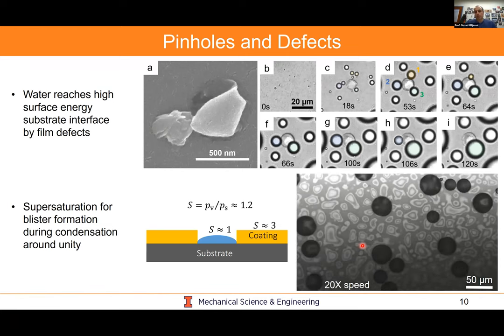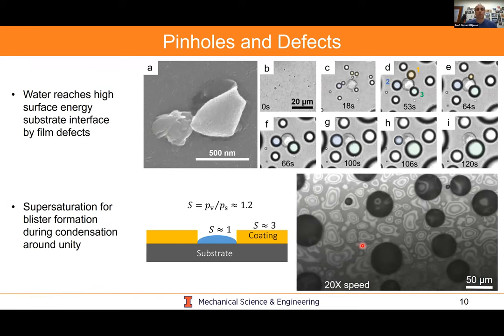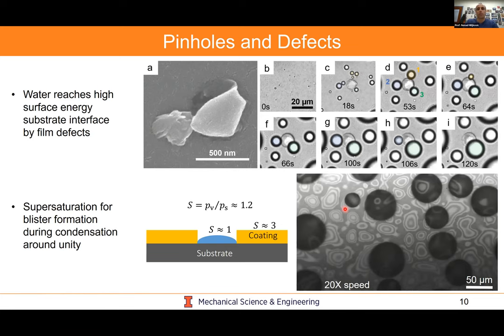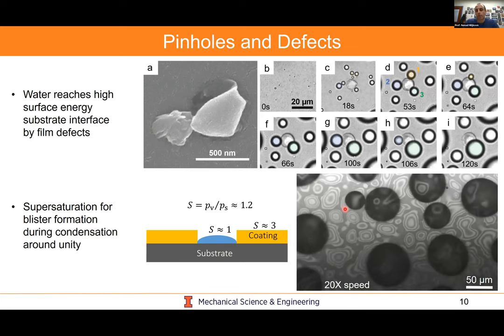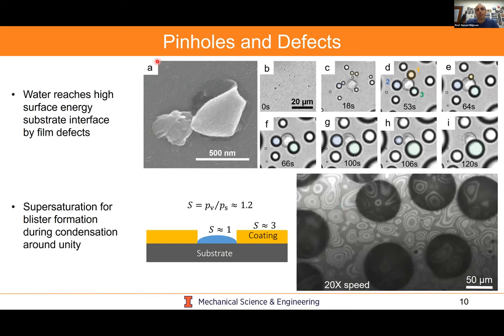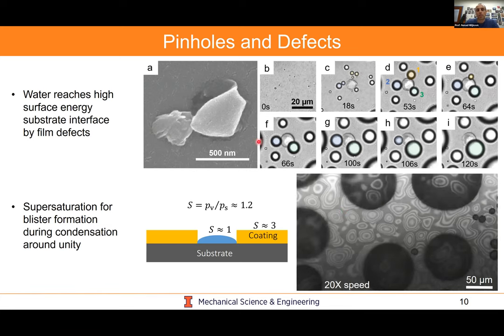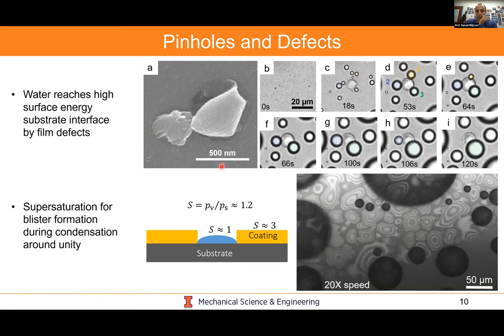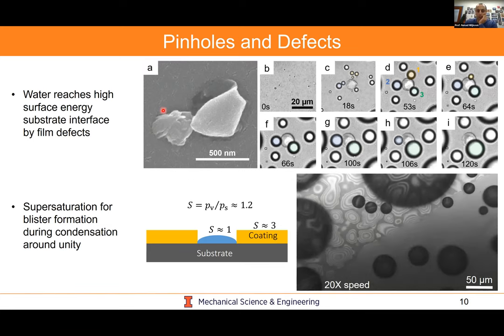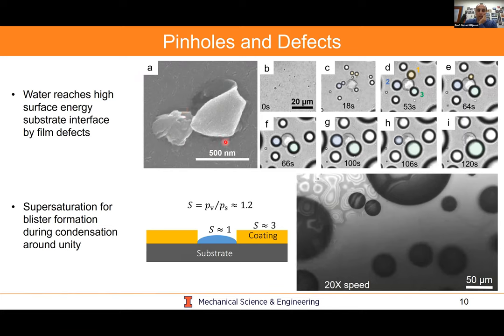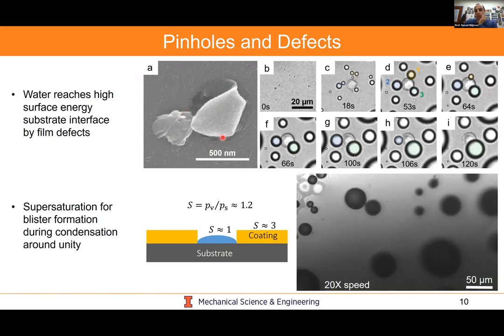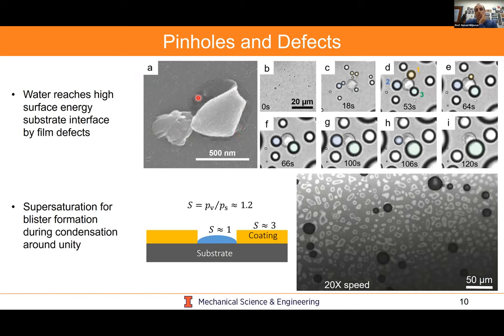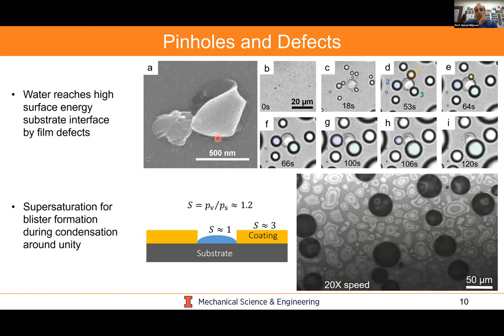So the first hypothesis we had, based on optical microscopy, was that these blisters are pinholes in the coating, and they're there because of defects during manufacturing. Typically, if you take one of these polymer films deposited on a silicon substrate and put it in a scanning electron microscope, you'll see small defects where, during deposition, a crack will form, or there'll be a dust particle on the surface, where the polymer coating will not be able to conformally coat the substrate.